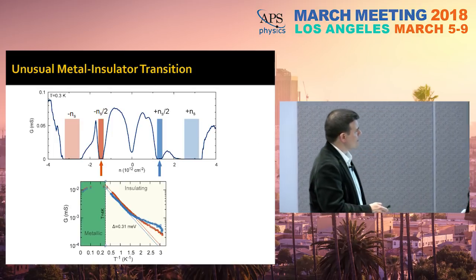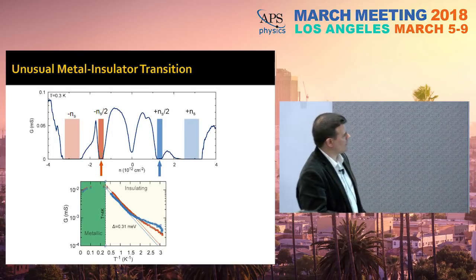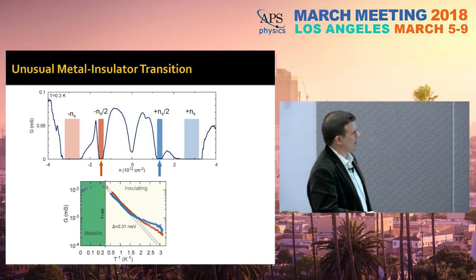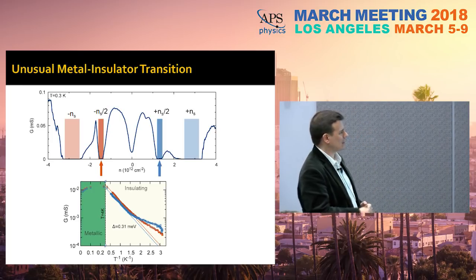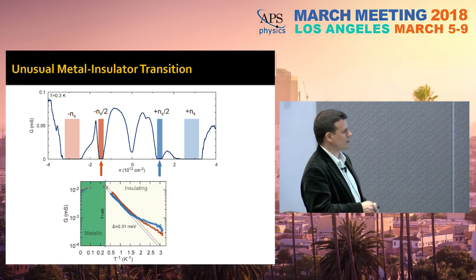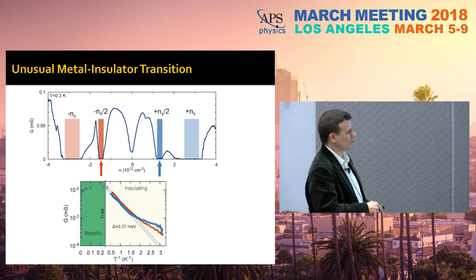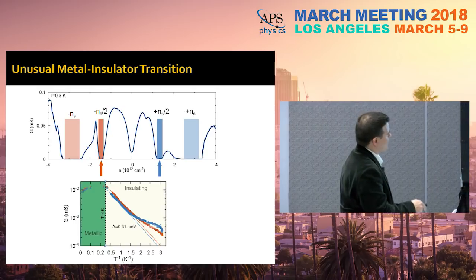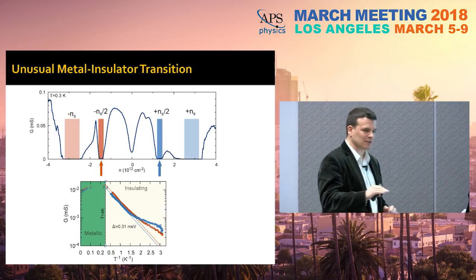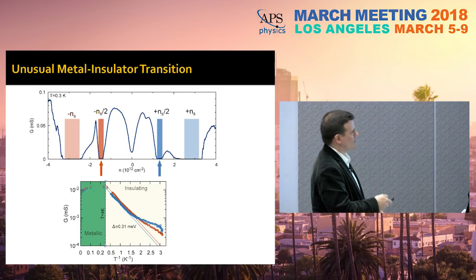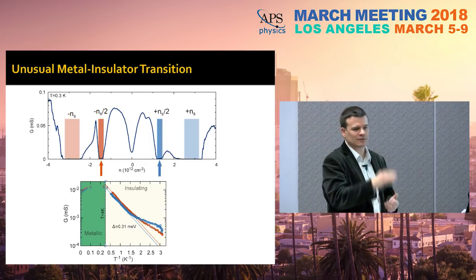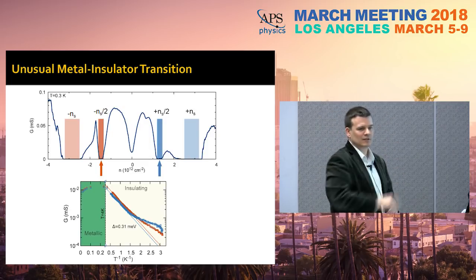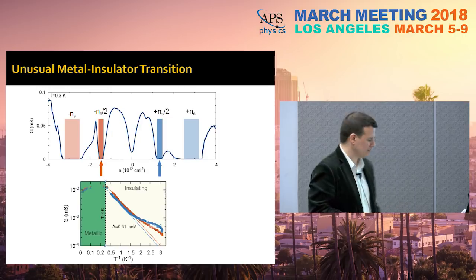So the first thing that we realized that was kind of unusual is that this system exhibits metal-insulator behavior. At high temperatures, it's a metal. At low temperatures, it's an insulator with an energy scale about 4K. This conductance goes as 1/T. Okay? So at about 4K, the system goes from a metal to an insulator. That's already unusual. All of the other insulating states are just insulators. Cool down, and it's always insulating. It doesn't exhibit this metal-insulator behavior.